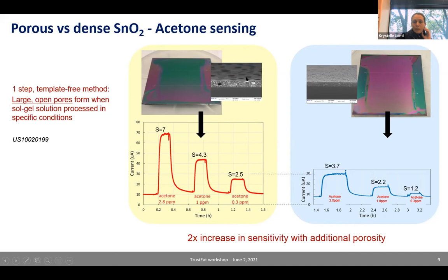And so when we did the same sensing experiments using acetone in those same low concentrations, again, we saw a 2x difference in sensitivity with the higher sensitivity obtained with higher surface area. So again, we see that surface area is critical and we need to maximize it in order to boost the sensor sensitivity. So similarly, we prepared other MOS sensors. We have by now a small library of MOS that we can play with.